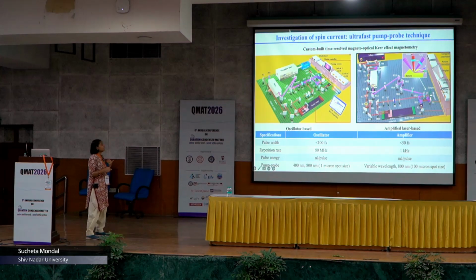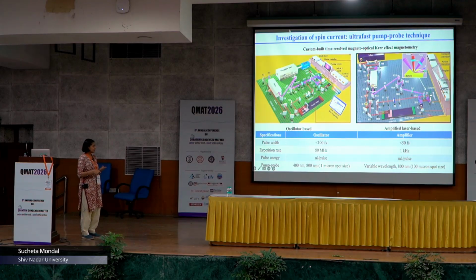So, the amplified femtosecond laser is a very powerful laser, and the repetition rate is much lower, about a kilohertz. So, the pulse energy is very high, and the pulse width is about 30 to 40 femtoseconds. So, we could probe ultrafast demagnetization nicely with really good resolution. This setup helps us in studying many fluence dependent studies, also wavelength dependent studies, because this setup comes with an OPA, optical parametric amplifier, as well. So, many of the laser parameters which might be useful for the audience are listed here.